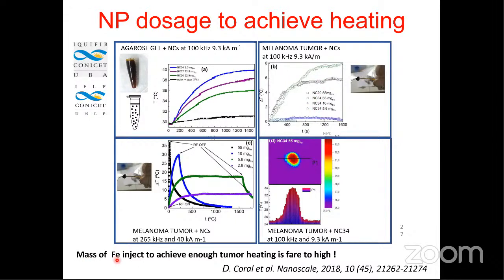So the mass of iron injected to achieve enough tumor heating at biomedical conditions of field amplitude and frequency is way too high. If you go to higher frequencies and field amplitudes, we have done this, you will have very nice heating. But at the biomedical conditions, the mass of iron that has to be injected is way too high. This has to be improved.